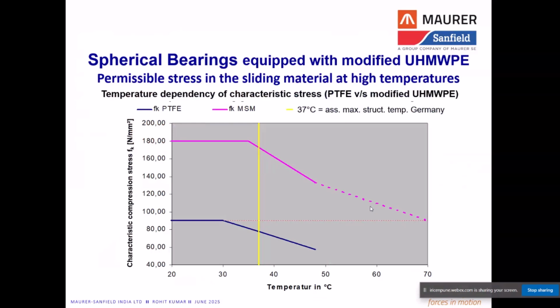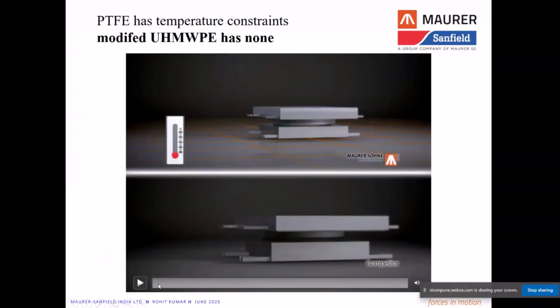This is one of the tests conducted over the PTFE and this UHMWPE sheet, and you can see the result here. The PTFE sheet completely failed at around 48 degrees centigrade, which is already mentioned in our IRC code also, whereas the advanced material can work up to 70 degrees centigrade. This is just an animation to show what exactly happens with an increase in temperature. I think there is some error, but it gives an indication that whenever the temperature rises, failure happens in the thermoplastic material, because thermoplastic material is temperature sensitive.